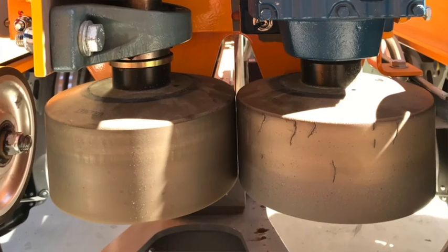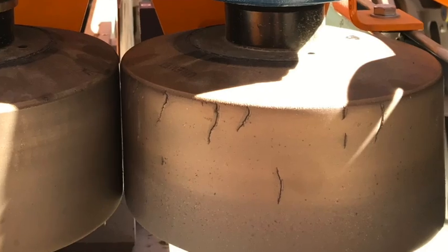They start doing what's called chunking out — where the wheel is going along just fine and it loses part of its urethane. They get cracks in them and just come apart. On a general rollercoaster, I actually plan on replacing about one or two wheels a week. Most of the time these aren't coming apart or chunking out badly. But depending on the ride, you can keep an eye on it.